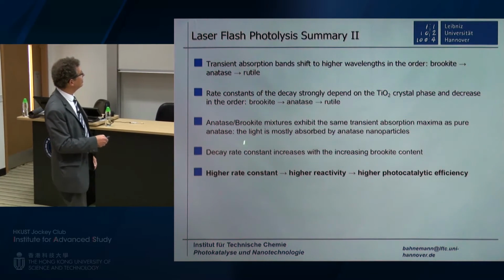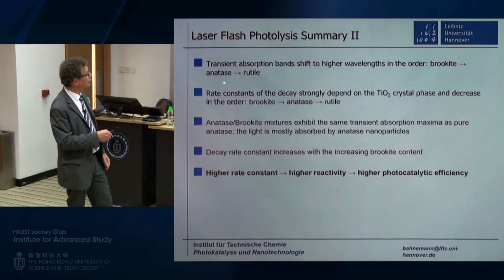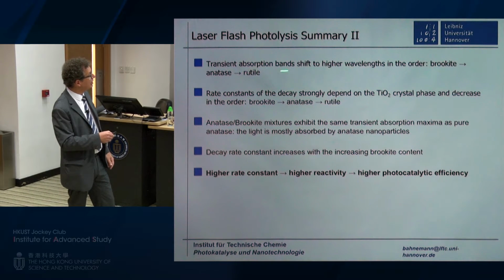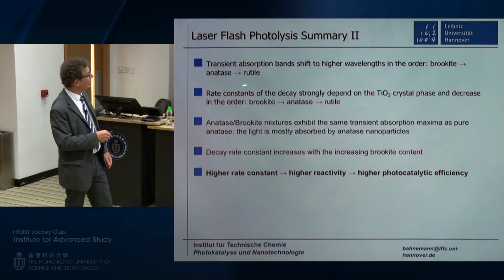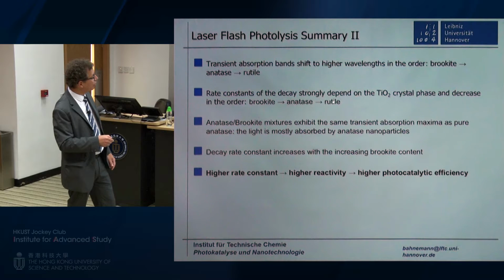And this is the final summary. So the transient absorptions are shifted in the order brookite, anatase, rutile. The rate constants depend on the crystal phase, and the decay rate increases with increasing brookite content.